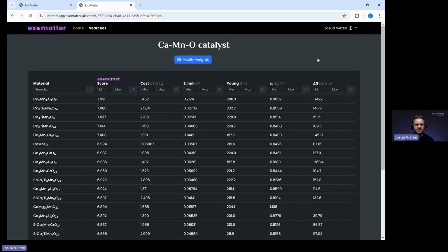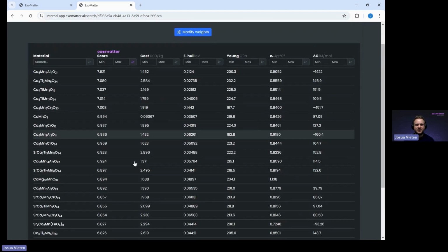And now what you can see is for all of these materials, you see your delta G and your heat capacity. So one of the most well-known ones is calcium manganese oxide. You can see that delta G here is positive, so it means that 800 degrees C and 1 millibar is not enough to completely reduce this material. But there are some other ones where it is enough.